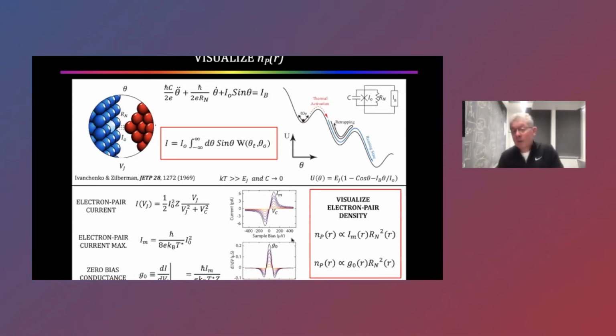So what Dynes showed is that you can measure the pair density in the sample by measuring either the maximum in the diffusive pair current or the value of the pair differential conductance at zero bias. And you have to know what the normal state junction resistance is. So either keep it constant or measure it, but then you can visualize the pairs.